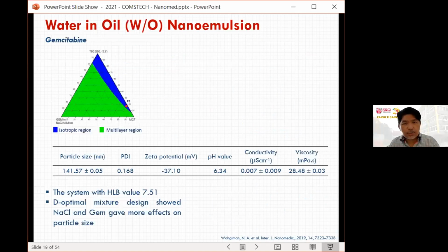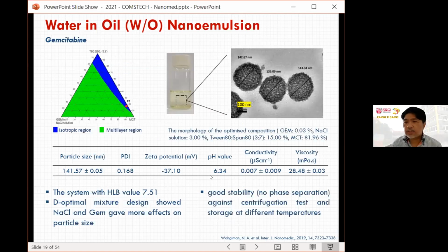Okay, now I use another nanoemulsion, which is water in oil, with gemcitabine. The process is very similar, except this one is a totally different approach. The idea is to get as much gemcitabine into the system. By using the optimal mixture design, we managed to get below 150 nanometer, consistent with the pH value and also the zeta potential. This again showed no separation after 3 months, even at 3 different temperatures, which is quite consistent.